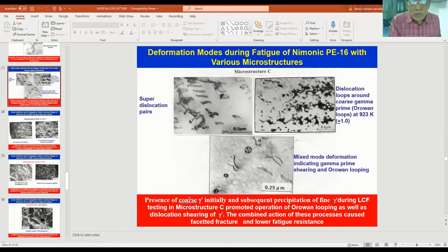Here I have given the presence of coarse gamma prime initially and subsequent precipitation of fine gamma prime during LCF testing. In microstructure C, it promoted the operation of Orowan looping as well as dislocation shearing of gamma prime. The combined action of these processes caused facetted fracture and lower fatigue resistance in the material.